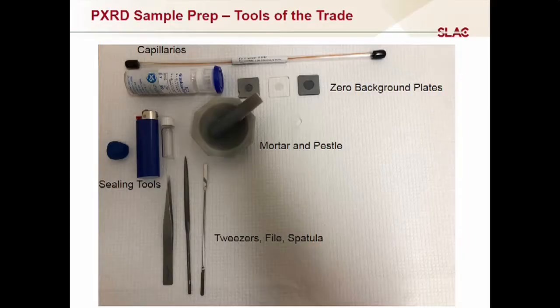So some tools of the trade. These are some of the things that you might be using when you're trying to mount a bulk powder for measurement. You can mount it in a couple of different geometries. So you can do it in a capillary. These are very thin-walled glass capillaries that you can buy. The wall thickness is about 10 microns. They're quite fragile. You can get them in regular SLS glass, in a slightly higher quality borosilicate glass, or in quartz. The quartz ones are actually fairly strong and resistant to much higher temperatures, which can be interesting depending on what you're doing. You can also use Kapton.